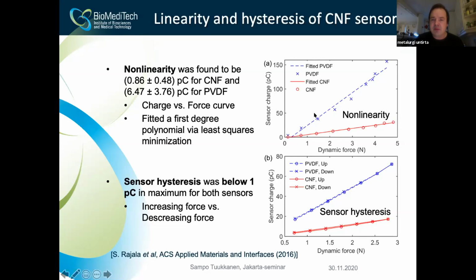And here we have measured with the commercial PVDF film, and it gives quite good linearity with our film as well. And another issue with the sensors is the hysteresis. So when you go up with the increasing force or you go down with the decreasing force, does it give a different output? If you have a very bad sensor, it can be this banana shape. But in this case, we have got quite a good hysteresis curve as well.